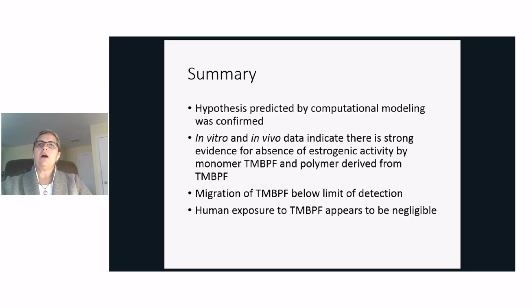My last slide is just a summary. Our hypothesis, initially drawn from the computational modeling, that TMBPF would not be an estrogenic compound was confirmed. All the data in vitro and in vivo, and additional data that you can find in the publication, confirms the lack of estrogenic activity by both the monomer and the polymer. The migration of the polymer is below the limit of detection, and this also led us to conclude that human exposure to the monomer appears to be negligible.